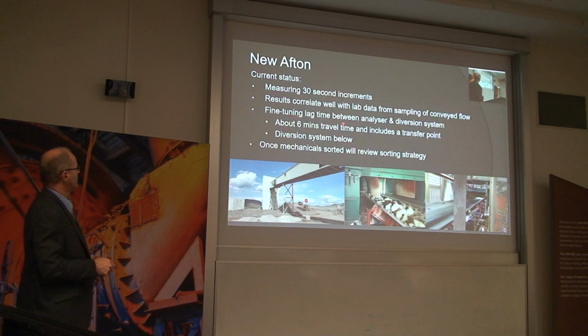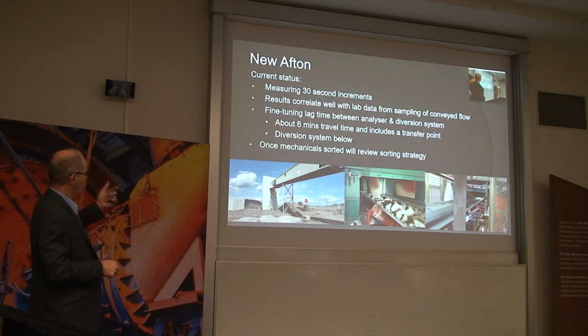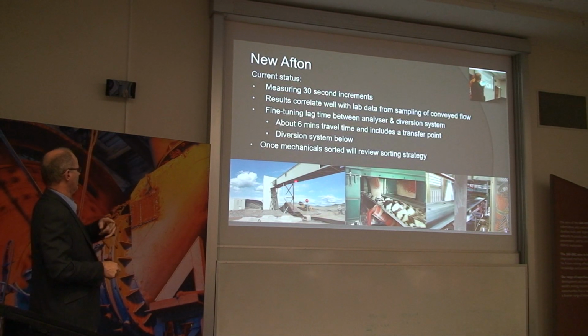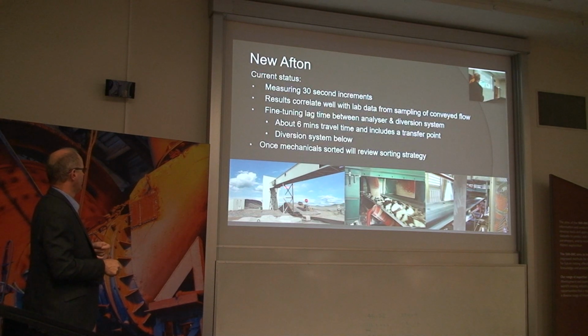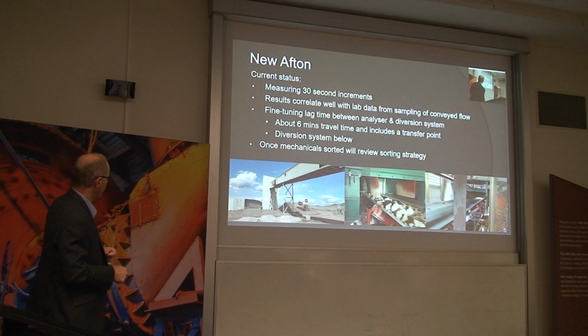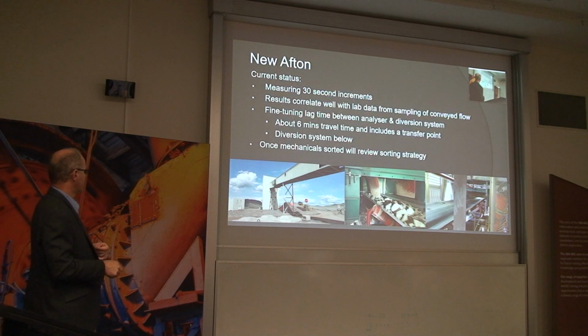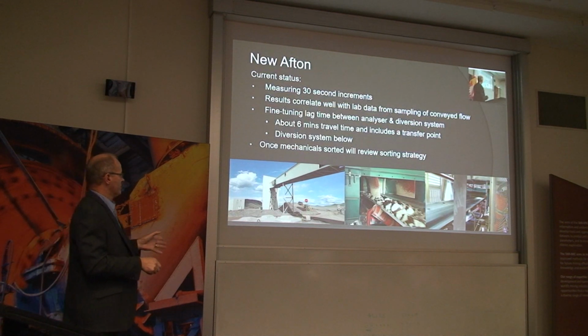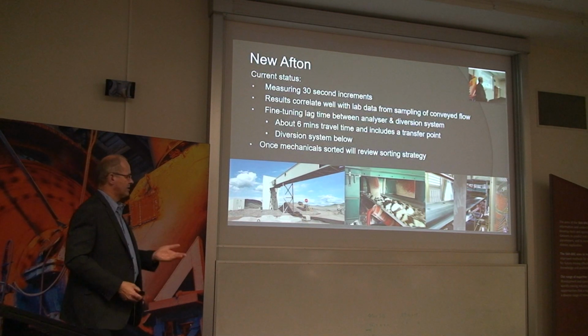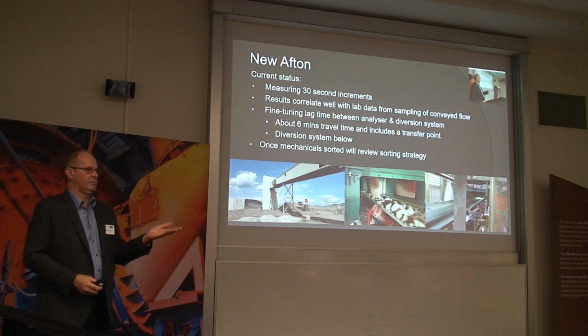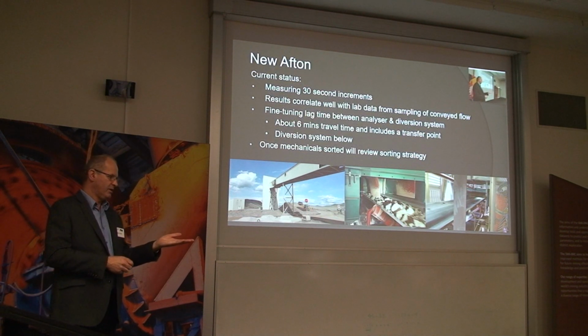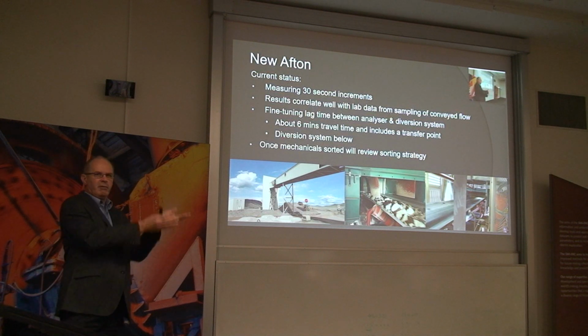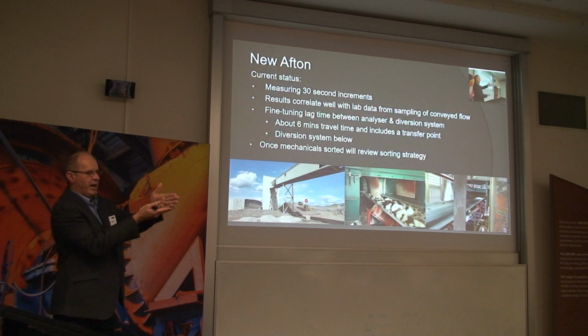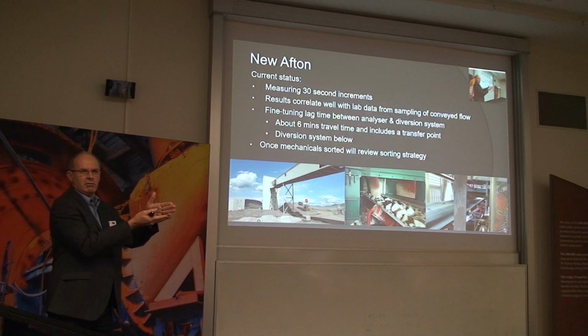They're fine-tuning the lag time between the analyzer and the diversion system, because the analyzer is 6 minutes travel time back down the decline from the diversion point in this conveyor. Crushed ore stockpiles in the background. This is the material that's being diverted that's considered waste. Their diversion system is a bit different. It's actually a hydraulically actuated series of lifters that lift the conveyor belt up, flatten it, and press it up against a fixed plough.